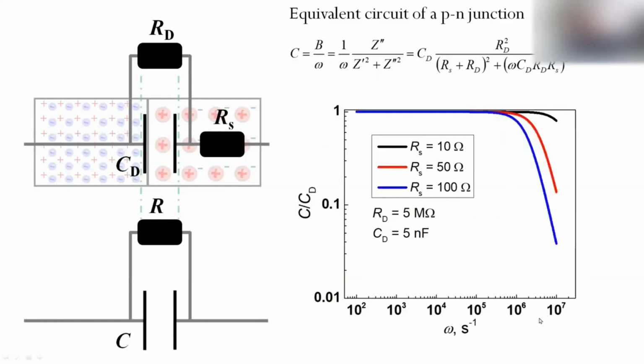So what is the benefit of using impedance spectroscopy? If we just operate with capacitance measured directly by our capacitance meter, it gives us the depletion layer capacitance multiplied by this complex factor, which depends on the resistance of the depletion region, frequency, and series resistance. If we compare the ratio between the measured capacitance and the depletion layer capacitance as a function of frequency, we see that at large frequencies, for large series resistance, we have a huge deviation. It's almost 2 orders of magnitude difference between measured capacitance and real capacitance of the depletion layer.